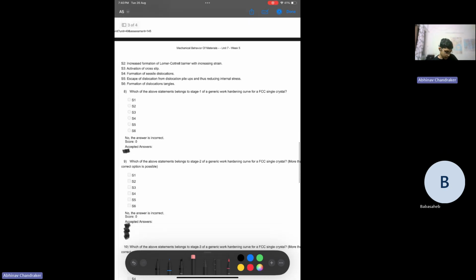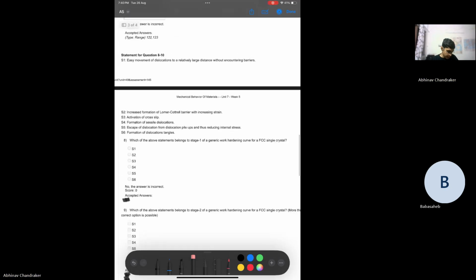So let's look at question 8. Which of the above statements belongs to stage 1 of a generic work hardening curve for a FCC single crystal? Stage 1 for a FCC single crystal. Let's see. Easy movement of dislocations to relatively large distances without encountering barriers. Yeah, that's stage 1.